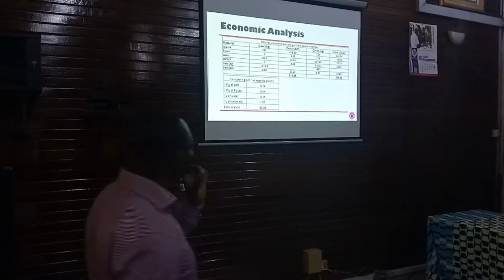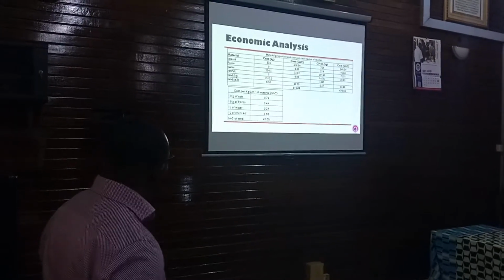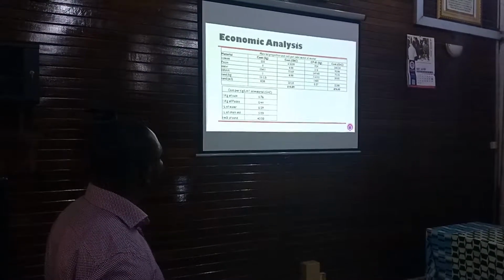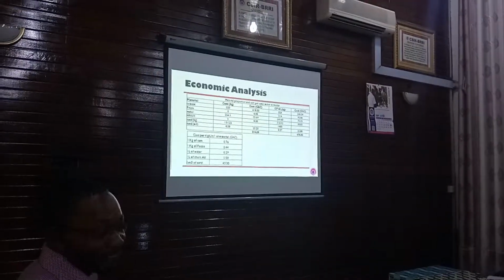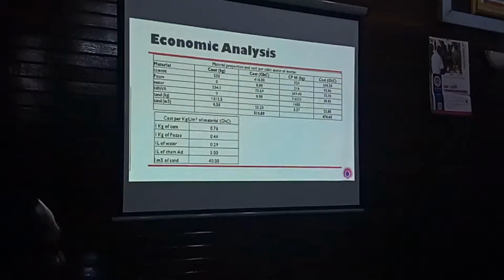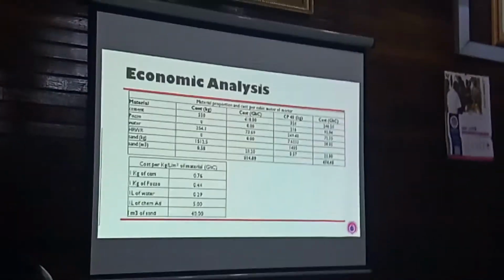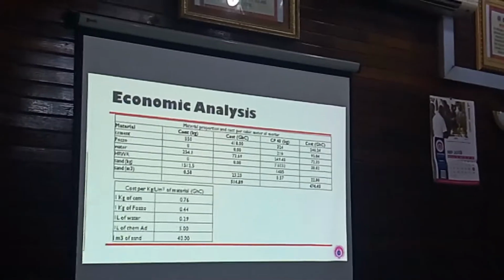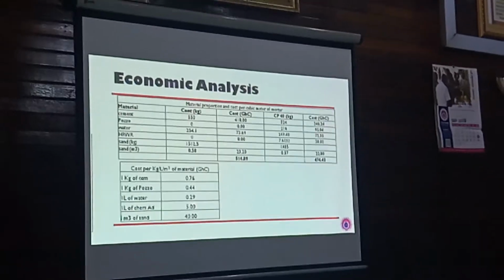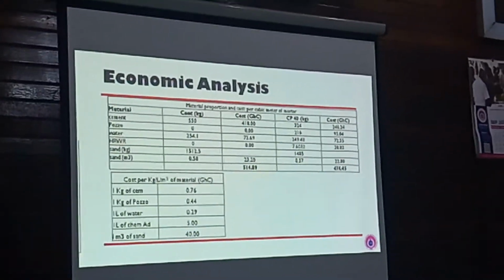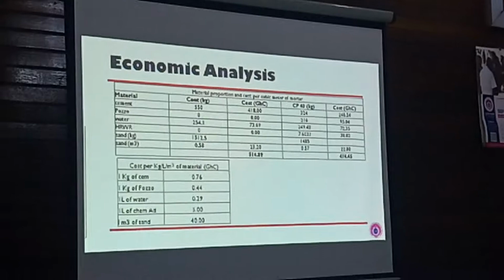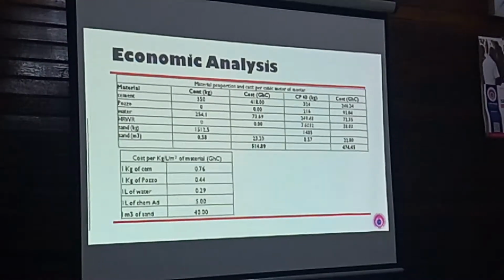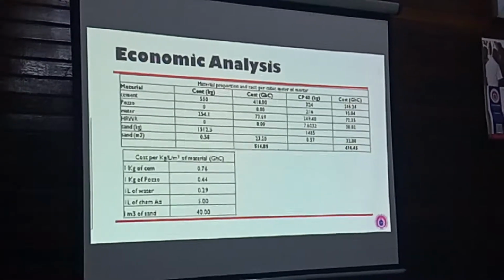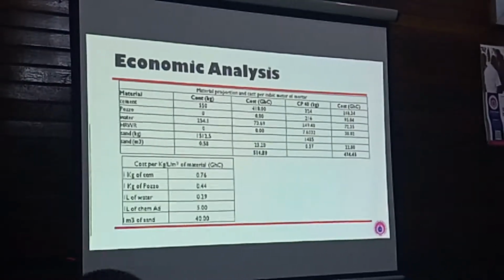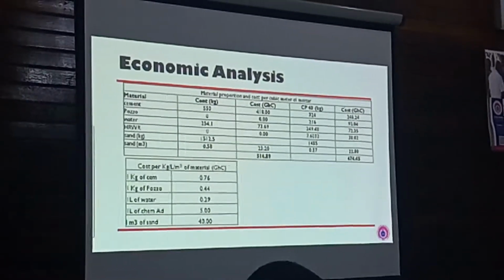Economic analysis, very important. So these were the basis for the economic analysis: cost per kilogram or per liter or per meter cube of the material that I use. 1 kilogram of cement, I estimated to be 0.76 Ghana cedis. 1 kilogram of pozzolan, 0.44, even though we can still bring it down. 1 liter of water, 0.29. 1 liter of the chemical admixture, 5 cedis. 1 meter cube of sand, 40 Ghana cedis.